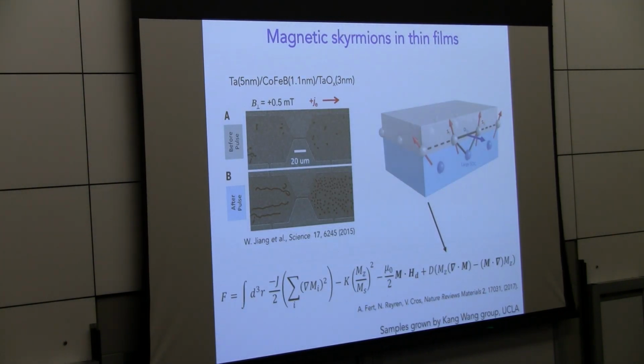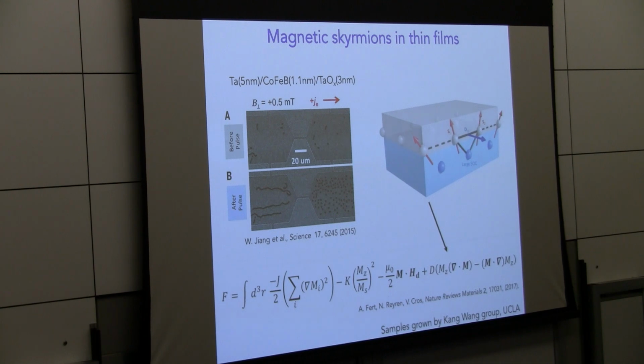We have collaborated with Kang Wang's group at UCLA, who grew a thin film sandwich of materials, in this case this structure, in which one can realize the necessary magnetic interactions to realize skyrmions. In particular, one needs some inversion symmetry breaking in order for what's called the Dzyaloshinskii-Moriya interaction to be non-zero. This is an antisymmetric exchange interaction that can happen in bulk crystals with broken inversion symmetry. And effectively, this interaction favors a non-collinear alignment of nearby spins.